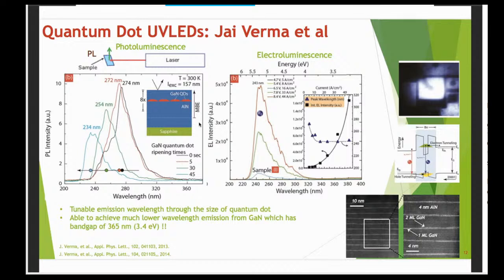The next step was to test it out by injecting current into the structure. So we fabricated LEDs. This picture you see is actually an LED structure that we fabricated. This small pin-like thing is a probe that is coming onto the LED and injecting current into it. The other probe is at the bottom of the structure. This glow is coming from the LED because in spite of all our good work, it would still emit some blue wavelength. Your normal camera cannot capture ultraviolet, but it can capture blue, so it could capture that emission from this structure.